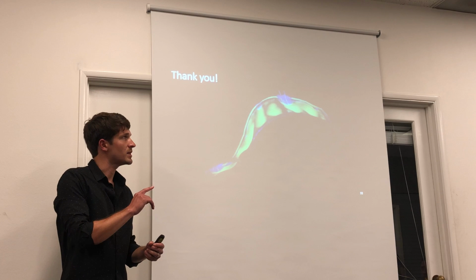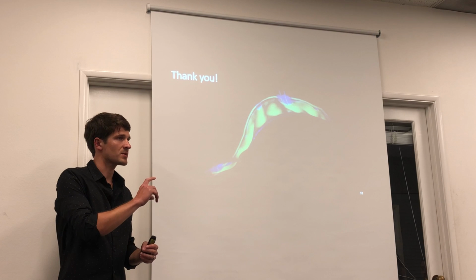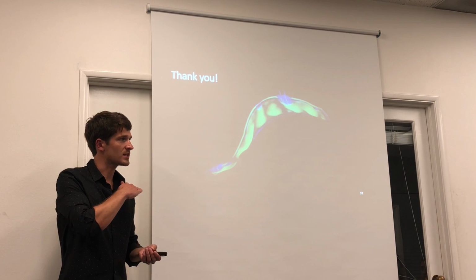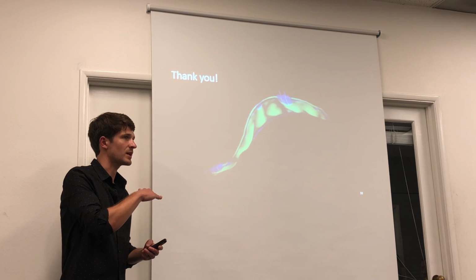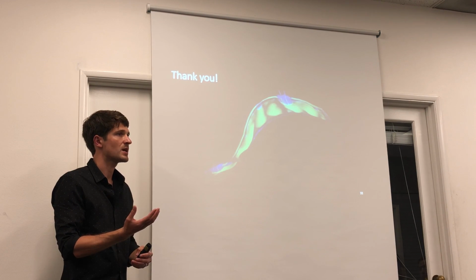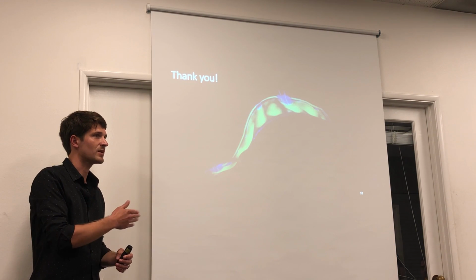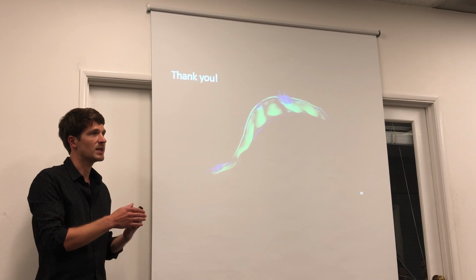And also the company that had the blimp, they are also working on a small scale actuator that uses these multiple layers. The challenge with multiple layers is that it's hard to get consistent thicknesses without defects between each of the layers. The one that I showed you, the quadrants, I think they have maybe 8 layers. The fish, I believe they're on the order of 4 to 8 layers. But when I was talking to him at the conference, he said that many of them fail. They go through a whole lot of failed ones because it's really hard to get high quality control of these devices.